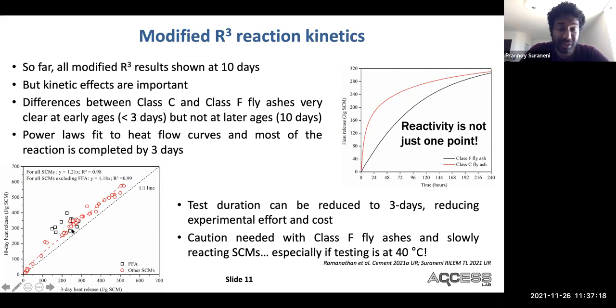But this is not the case for class F fly ashes. You can see that they have a completely different relationship here. And if you're reducing the test duration to 3 days, it's certainly possible, but take a look at your curve. If your curve is looking like this, reducing to 3 days might not be a good idea. If your curve is looking like this, you're probably okay reducing the test duration. So a lot of caution is needed with class F fly ashes and other slowly reacting supplementary cementitious materials when you consider reaction kinetics.